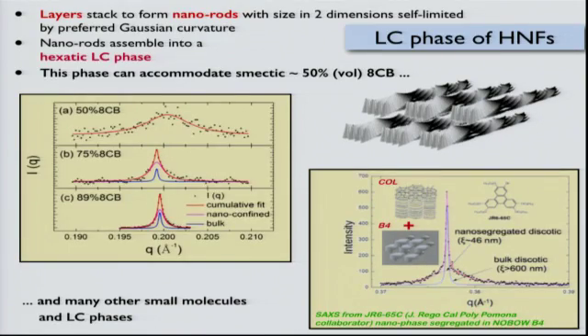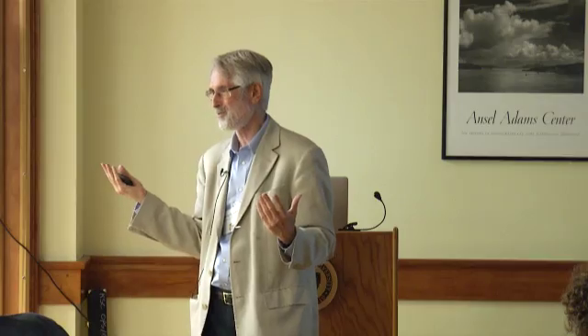And this phase, the most amazing thing about it, it's a liquid crystal of these nanocrystals. It's a hexatic liquid crystal of nanocrystals, and this phase can accommodate almost anything, up to like 50% by volume. Almost anything. I mean, it's amazing how you just melt the NOBOW and stick something in there, 50% by volume, and cool it down, and the guest, it's a host-guest thing. Really, we're doing host-guest chemistry in the helical nanofilament phase. So you cool down, and the guest is nano-confined.